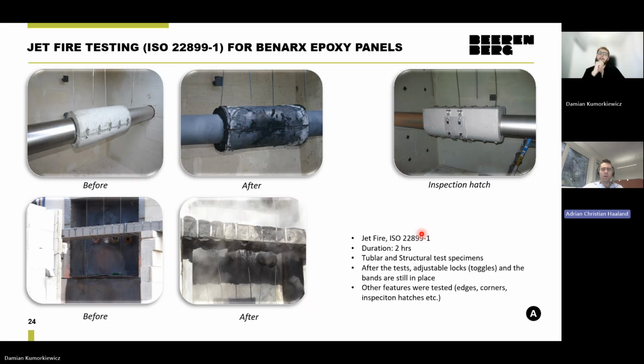And these pictures show you a little bit how a Benarx epoxy box will look and react during a jet fire test. This is a fairly thin box, so you will see that the PFP is actually eroded away. You can see the steel coming out on the middle top picture here. And then, of course, we have the Chartec on the inside, which helps to protect the object during the later stage of the fire. We included an inspection hatch to test that this does not represent a weakness in the system. And on the bottom here, you can see an example of a cable tray configuration test where we actually run electrically charged wires inside the cable tray to see that they could actually withstand the rated current during the fire scenario.